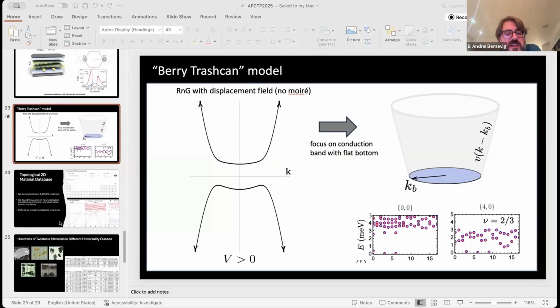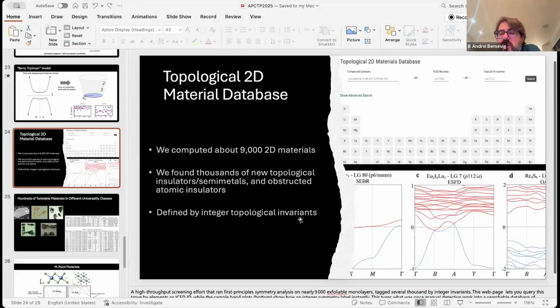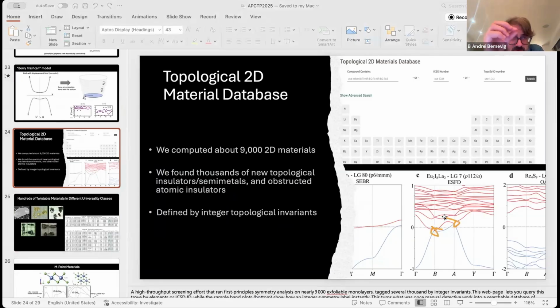And these are just in the experiments that exist. There's new stuff. Basically there are many universality classes of systems. You can twist, for example, in a square lattice, you can twist these points. The Fermi level is there. So there are many classes that will give you different Hamiltonians, with different degrees of freedom, that will give you different states of matter. We don't know the full extent of this possibility, especially since the phase space is huge, because you can take two materials, three, same, different, and twist them by a continuum angle. So from a purely theoretical standpoint, it's also very interesting, I think.